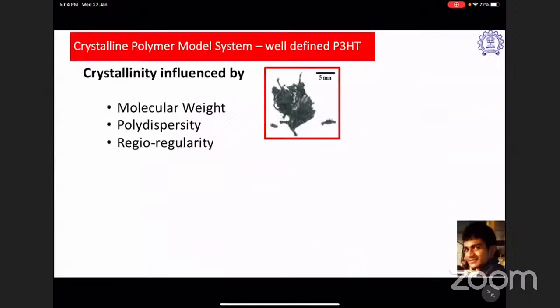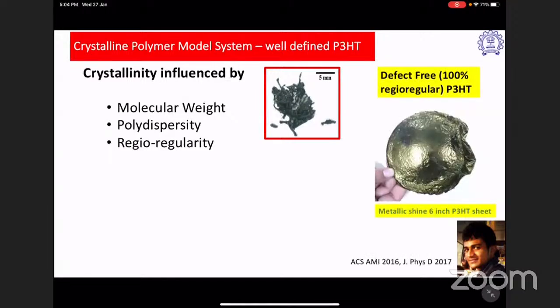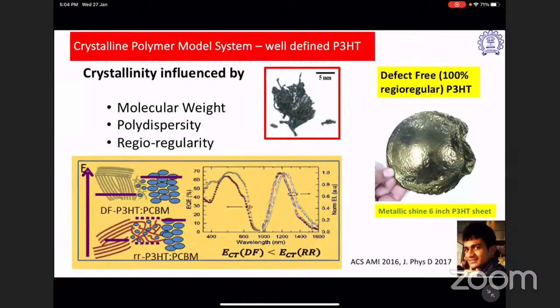But we had something different today, and lots of such things were happening, and we were also trying out these fullerenes using our classical P3HT system. Naresh did his PhD with us, and we got something very shiny like a silicon wafer. This is a defect-free P3HT from Anil Kumar, our collaborator, our colleague in the chemistry department, who makes ultra phase pure P3HT. It's a 6-inch big sheet of the conjugated polymer which shines like a metal, and we demonstrated